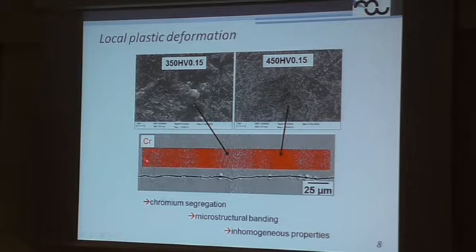We conducted element mapping along the fatigue crack growth front, and we see that the chromium content is alternating. So we have areas with a surface roughness, so with local plastic deformation, and in these areas we have less chromium, which leads to a microstructure with a coarse martensitic structure and less pronounced chromium carbides. On the other hand, where we have enough chromium, we see a much finer martensitic microstructure and more pronounced precipitation of fine chromium carbides. Additionally, we also conducted micro-hardness measurements, and this value in comparison to this value gives a good explanation why we have concentration of local plastic deformation in these areas.